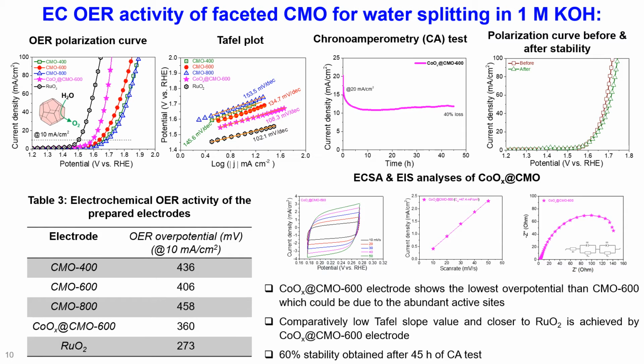So we were interested to incorporate the CoOx co-catalyst on the CMO 600 electrode by the dip coating method. Here, as expected, CoOx on the CMO 600 electrode exhibited 360 millivolt overpotential at the same 10 milliampere per centimeter square current density, which is closer to the standard ruthenium oxide electrode. Then the corresponding Tafel values of all the electrodes have been shown here.